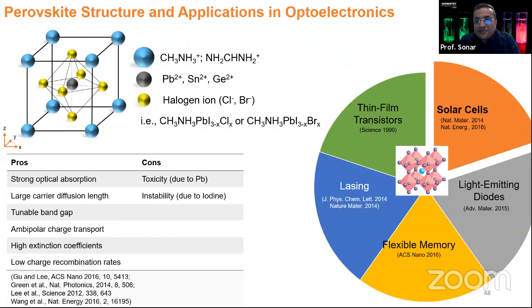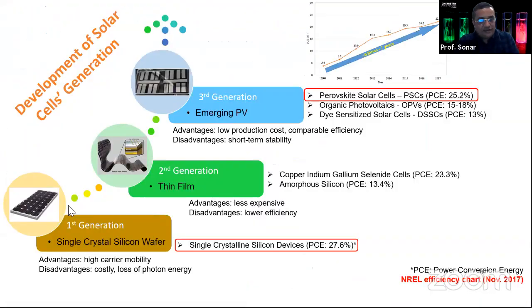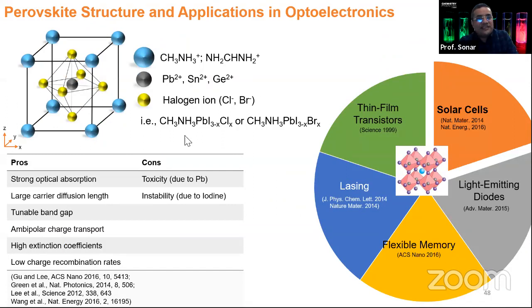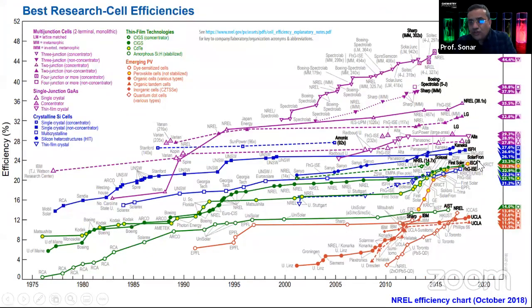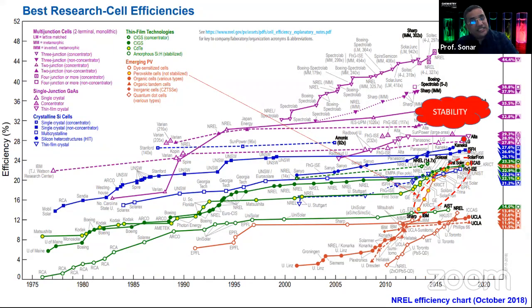So then we got to the solar cell. It might be that time is too short, but I'll quickly show you some of this organic solar cell technology, where there is single crystal silicon, and second generation and third generation, which is emerging: perovskite, organic and dye-sensitized. My group is working on perovskite, and we are particularly developing some new materials. The perovskite is a very nice high quality material, and looking at the solar cell data, perovskite is heading close to 26% efficiency. This is one of the fast moving, highly efficient solar cell devices in the world in terms of performance, but the stability is a big issue.